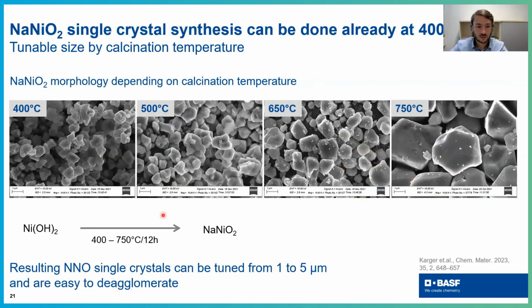So we have synthesized sodium nickel oxide first at different temperatures. And you see here the micrographs from 400 to 750 degrees. You can make single crystal sodium nickel oxide, and you can actually already here perfectly size tune this material. So you see that the size at 400 degrees is around 1 micron, and if you go to 750 degrees, then your size is around 4 to 5 microns. And this is really very nice. And then, well, the question is how to make LNO out of that.